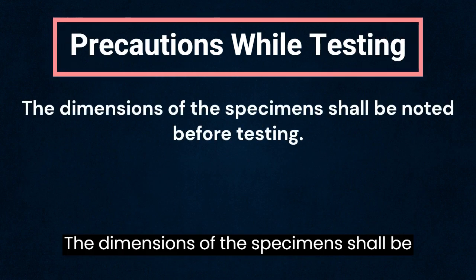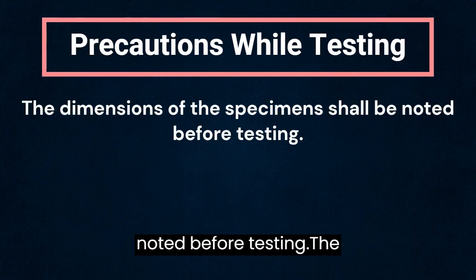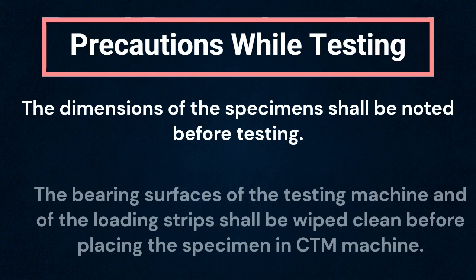Surface water and grit shall be wiped off the specimens and any projecting fins shall be removed from the surfaces. The dimensions of the specimens shall be noted before testing. The bearing surfaces of the testing machine and of the loading strips shall be wiped clean before placing the specimen in the CTM machine.